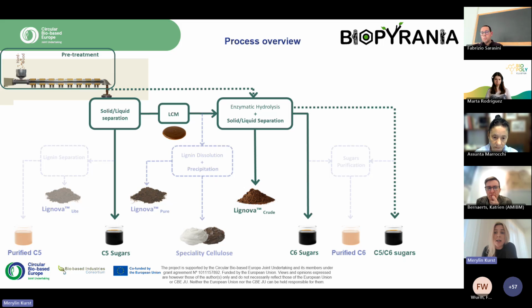The alternative route is that the lignocellulosic mass goes into the enzymatic hydrolysis, and the enzymes break down the cellulose into glucose. And after solid-liquid separation, we get the Lignova crude and the C6 sugars. The C6 sugars can also be further purified, for example, by adsorption. In addition, there is an alternative process configuration where the C5 stream is not separated from the slurry. Instead, the slurry goes directly into the enzymatic hydrolysis, and we get C5-C6 sugars.